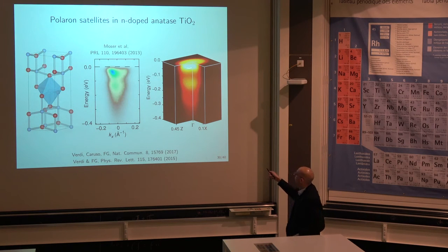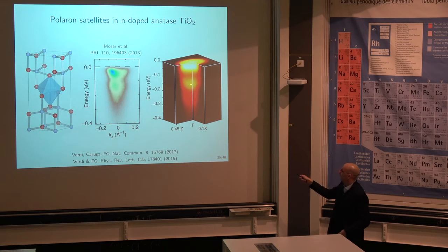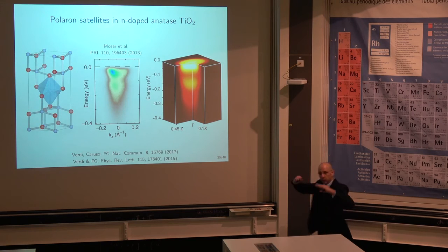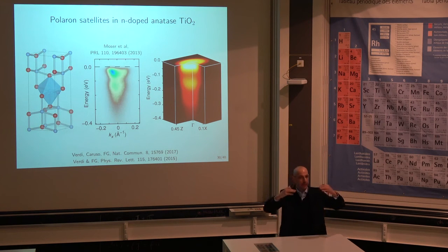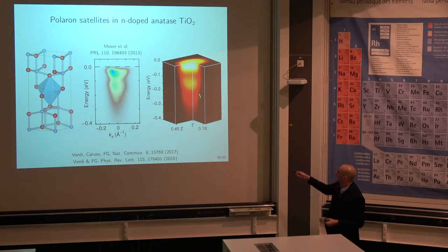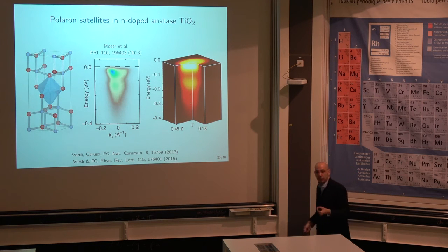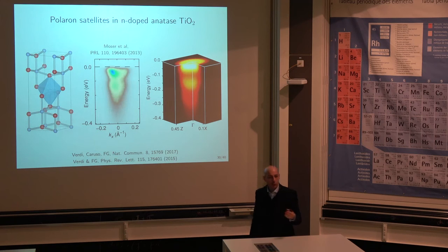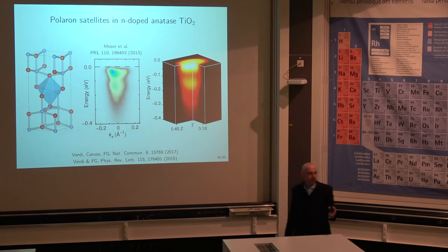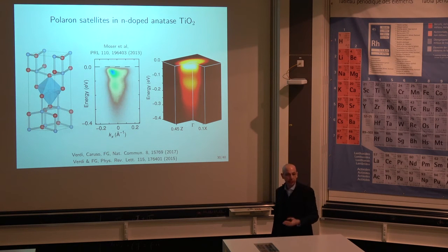What we are seeing is our main line here, which is the counterpart of that, the quasi-particle band. The first satellite, which is this one, is the counterpart of that, and the second satellite should be the counterpart of that. If you analyze them one by one and compare the energies, believe me, they match with the experiments. What you discover is that the separation between the quasi-particle band and the first satellite, and between the first and second satellite, corresponds to the highest longitudinal optical phonon in titanium dioxide, which is about 110 millielectronvolts. That's what people call a polaron satellite or polaron replica.